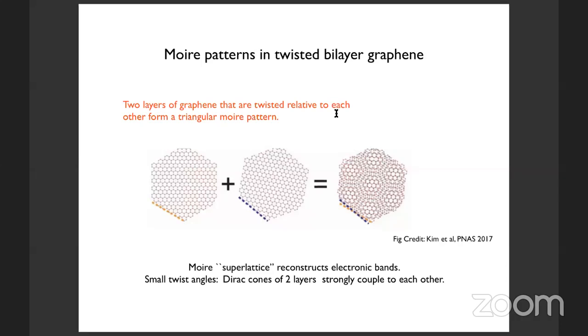All right, so this topic has gotten a lot of attention in the last 2 years. I presume all of you have heard at least a little bit of what's going on. So Moiré patterns and twisted bilayer graphene. If you take 2 layers of graphene that are twisted relative to each other, take 1 layer of graphene, put it on top of another layer of graphene with a slight twist, then the interference between these 2 crystal patterns leads to this Moiré structure, which on the face of it forms a triangular lattice, right? And with a period that is much bigger than the period of the individual graphene lattices.